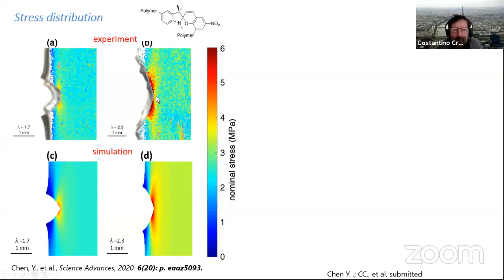Now, the advantage of this measurement is that you are measuring the stress directly. So it's not a digital image correlation measurement. We are not getting the stress from the strain. We are actually introducing a stress-sensitive probe inside the material. And by looking at the activation of that force-sensitive probe, we can actually directly measure the stress. So I think it's something really different from other methods. Of course, you need to embed it in the material, so you need some chemistry, but it's still something that we find pretty exciting to use.